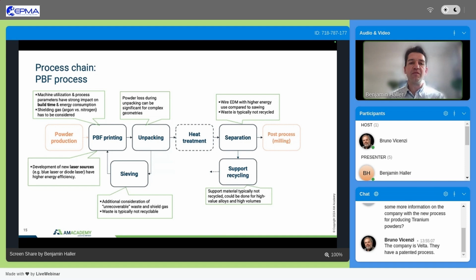And then for powder bed fusion, but basically for all powder technologies, what has a quite strong impact is the losses that you have, both during the printing process, where powders are being stuck or blown into the filter, but then also during sieving and unpacking. And this is basically the case for all additive manufacturing technologies today: support structures or waste are basically not recycled. This could be done, but it doesn't make so much sense for this very low volume. So typically this is not being done.